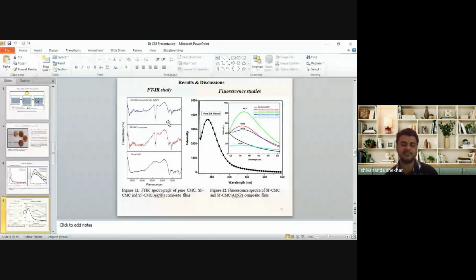So in the FTIR spectra, we got some functional groups present in the CMC as well as silk fibroin solutions. We can observe a peak around 1500 and 1600. This is due to the presence of amide 1 and amide 2 components present in the silk fibroin solution, as well as this peak is due to the conversion of Ag ions to Ag0, because there are several amino acid residues present in the composites, but here one particular molecule, that is the tyrosine molecules, is very responsible for the reduction of Ag+ to Ag0 nanoparticles.